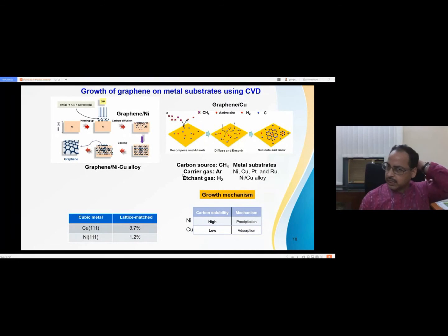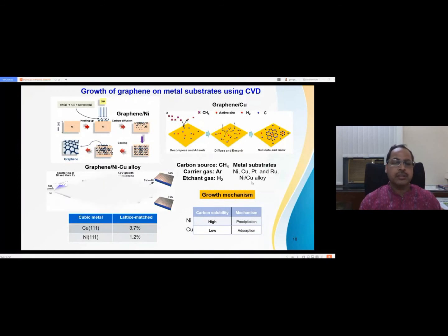The carbon source here is methane, and the metal substrates people generally use are nickel, copper, platinum, or ruthenium. Now people are also using nickel and copper alloys. I'll talk about Professor Rodney Ruoff, who is the pioneer in graphene growth on copper. Now he is mostly trying different nickel copper alloys like 90/10, 80/20, 70/30, different compositions, and you have to find what the actual growth mechanism is.